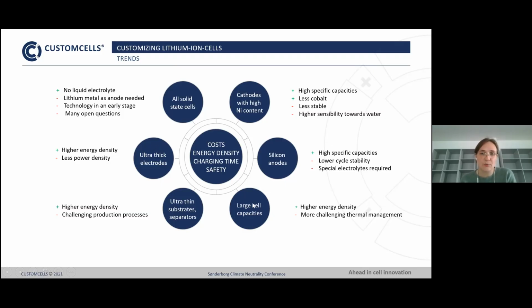Cells are getting larger, more and more, to gain higher energy density per cell. However, the thermal management can be challenging the larger a cell gets. Ultra thin substrates and separators are also in trend to gain higher energy densities. However, always keep in mind that the challenge remains in producibility of these materials. The electrodes are coated thicker and thicker, so the electrode loading gets higher and higher, which can result in less power density.